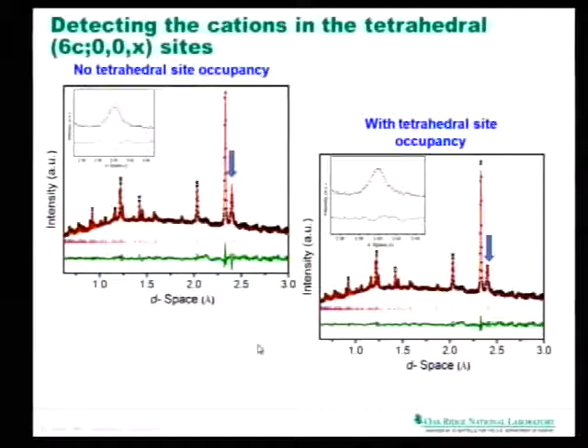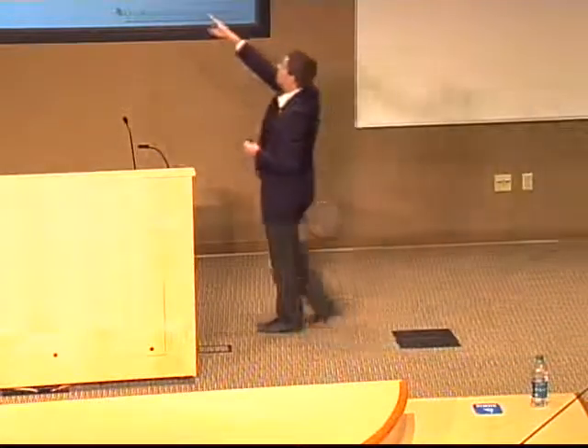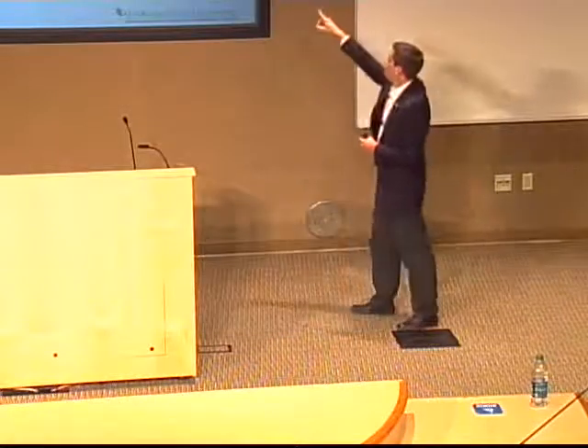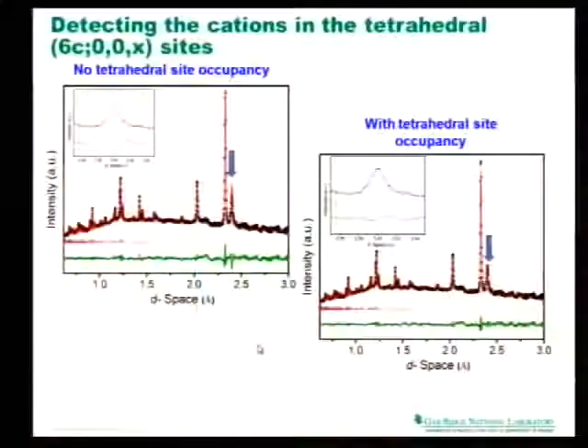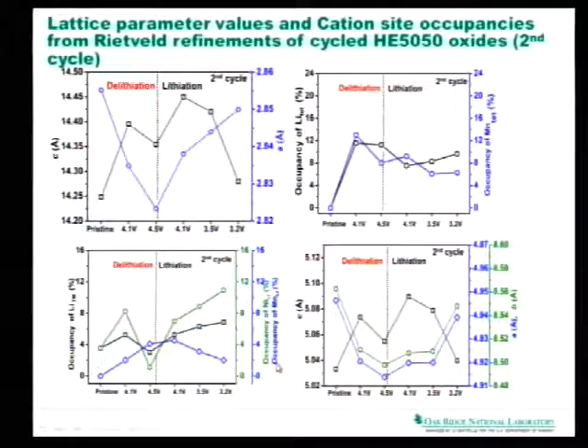And there again, some neutron diffraction patterns which allow us to see our ions sitting where they are supposed to sit. So this is not the nickel-lithium swap. This is where lithium all of a sudden sits in a different site. And in this case here, if you just look at your pattern and you model your regular structure with no defect in it, again, that peak marked here does not fit your experimental data. As you start putting your ions into tetrahedral sites and you start fiddling around with that, you make it fit. So you can determine where your atoms are sitting at which time. And you can see how my ions are floating around here. So we're constantly looking at nickel and manganese, for example, getting into lithium sites, stealing us capacity, as well as messing around with our voltage on that material.